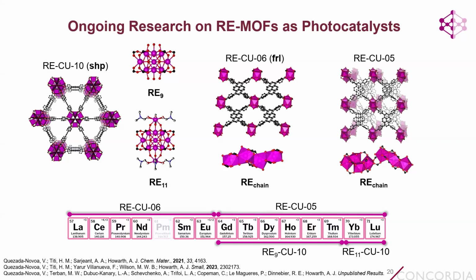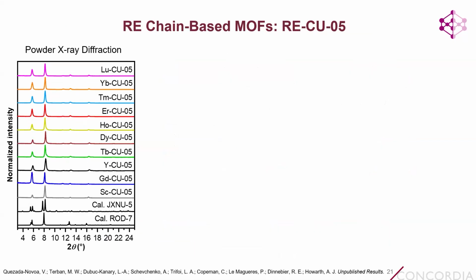But no matter how hard Victor tried, he was unable to make large single crystals of these MOFs that were suitable for single crystal X-ray diffraction. So I'm showing the structures here now because we know what they are. But at the time, we had no idea the structure of these MOFs. All we had were some powder X-ray diffraction patterns. And so to probe further and to actually understand the structure of these materials so that we could understand their properties and their photocatalytic activity, we needed to dive a bit further.